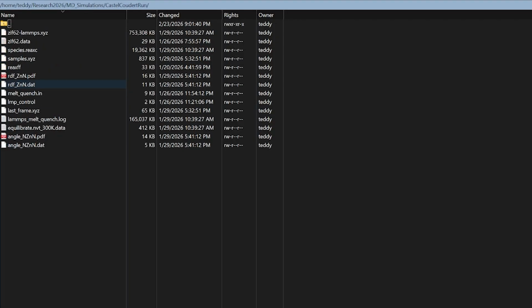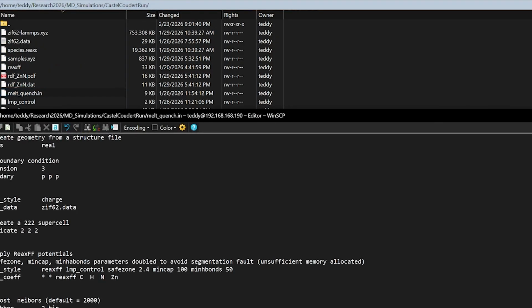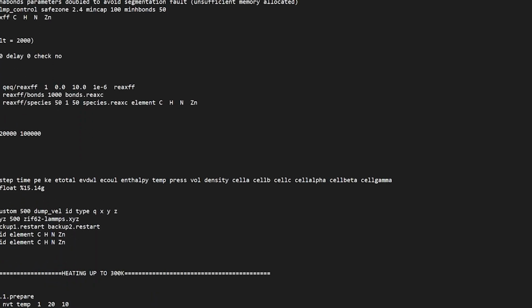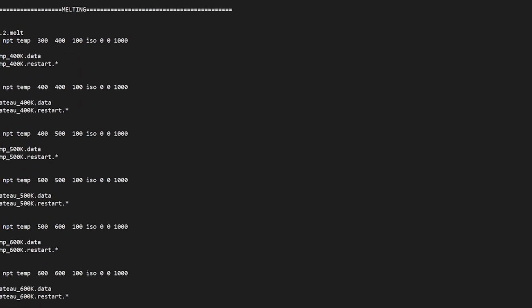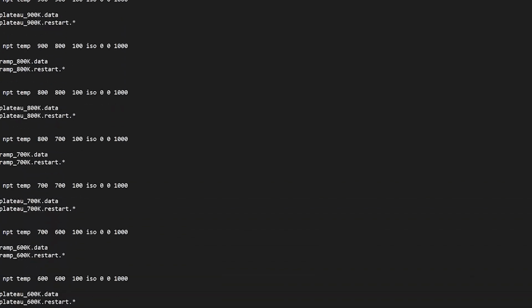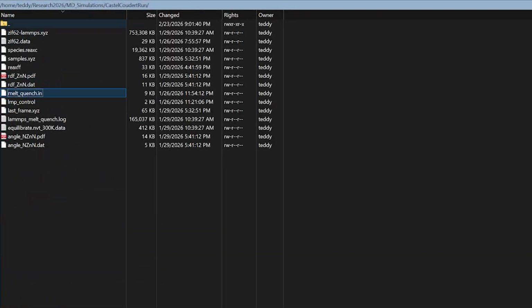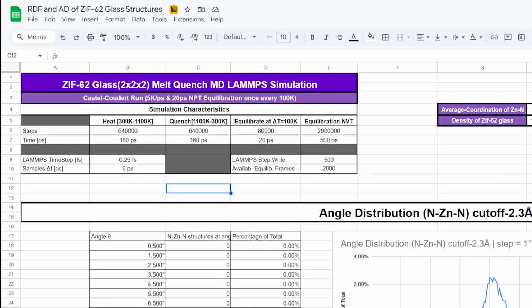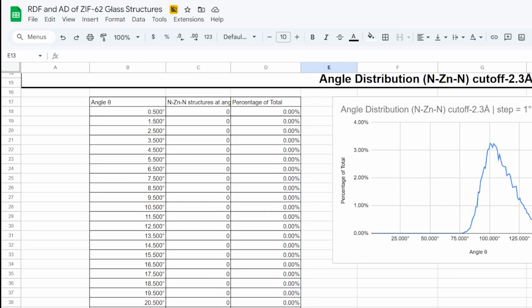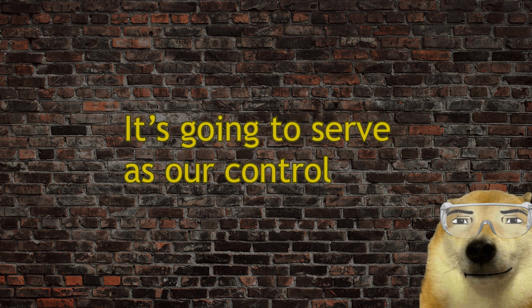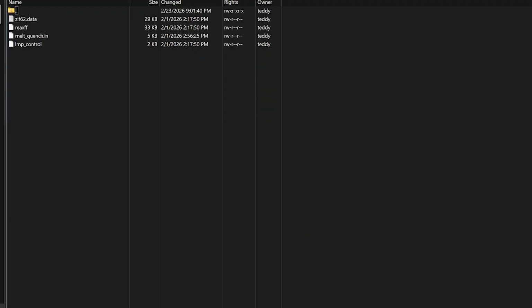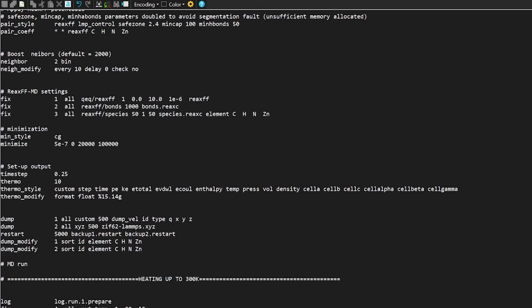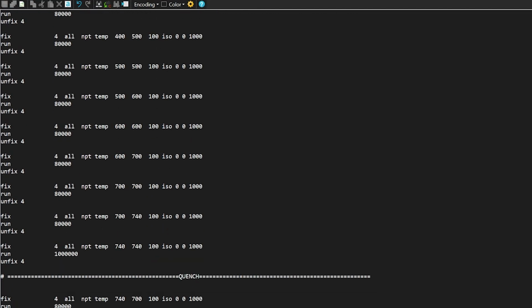The first trial we did, called Castell-Coulthard, would act as the control. This is the standard ReaxFF melt quench procedure that Castell and Coulthard deemed best for ZIF-4 in their paper and is widely used in literature. The system is heated stepwise up to 1100 Kelvin with equilibration pauses every 100 Kelvin, and then cooled down in the same controlled way. This method is considered reliable and is often used as a reference for comparison with more accurate quantum simulations.